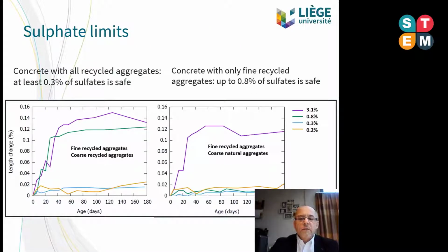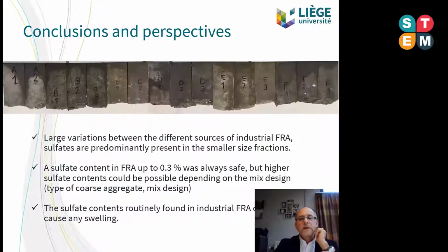So finally, we can conclude that the limit, which was at 0.2%, is too restrictive, and we could go at least for the sulfate content of recycled materials up to 0.3%, and for a concrete where only fine recycled material and natural aggregates could be used, we could go up to 0.8% of sulfates without any problem. So these are the main conclusions of this investigation.